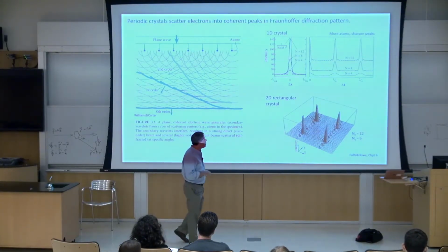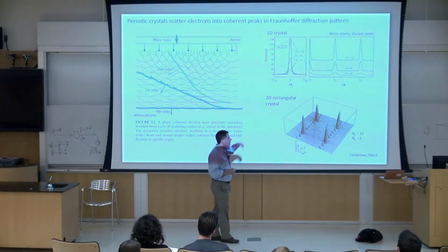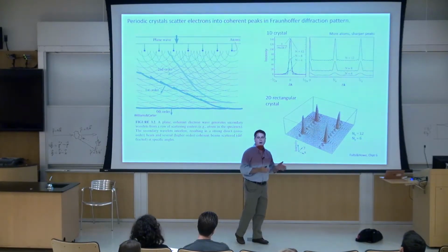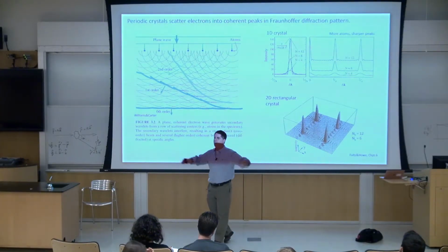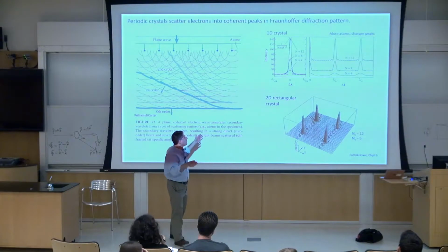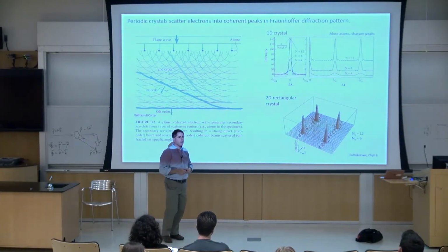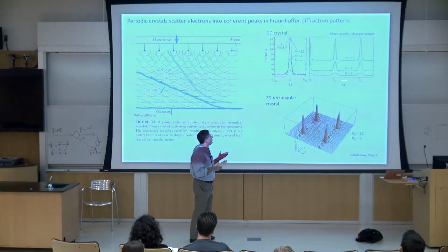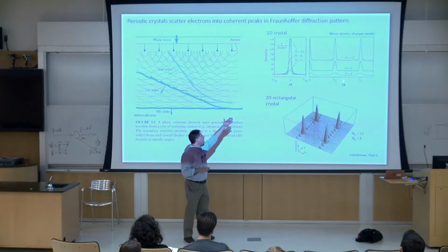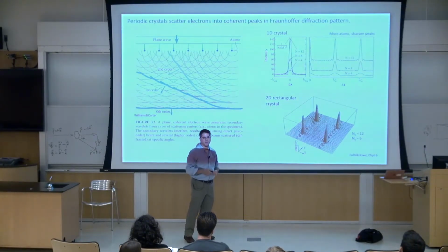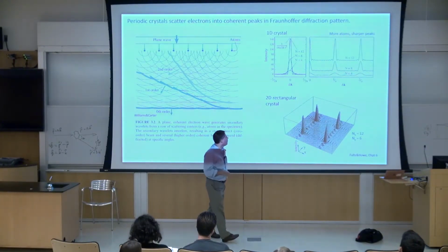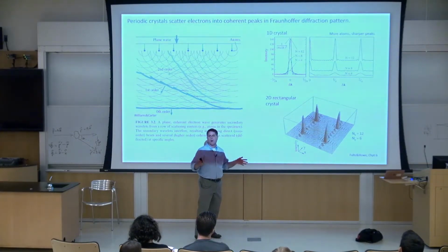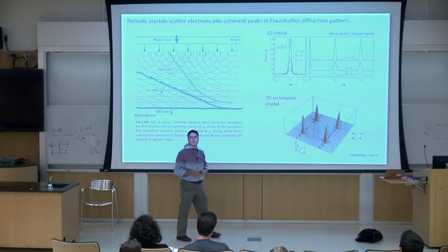The rule of thumb is if my object was 1 atom wide, the diffraction peak would be as wide as that diffraction peak is. It would be very boring. 4 atoms wide, it's 1/4 of the distance between them, and then 1/10, it's 1 over n basically for the width. And so, by the time I've got a nanoparticle that's 10 atoms across, it's developing a fairly respectable looking diffraction pattern.